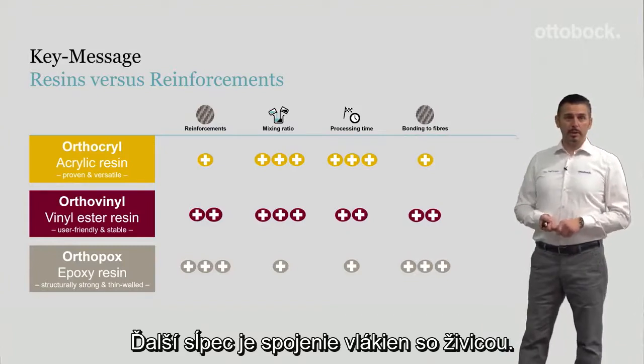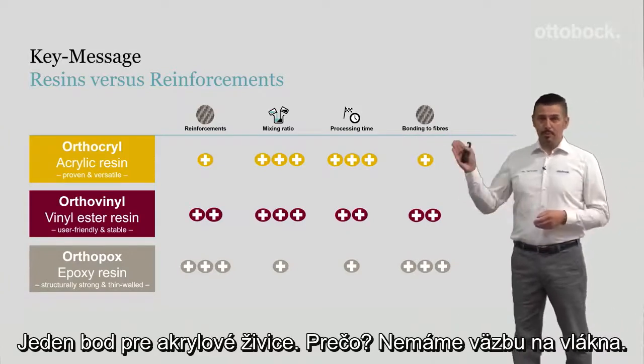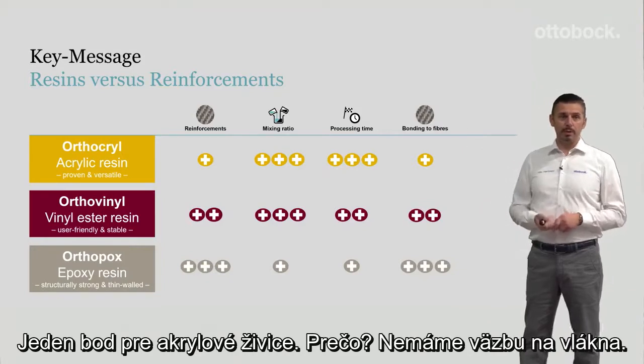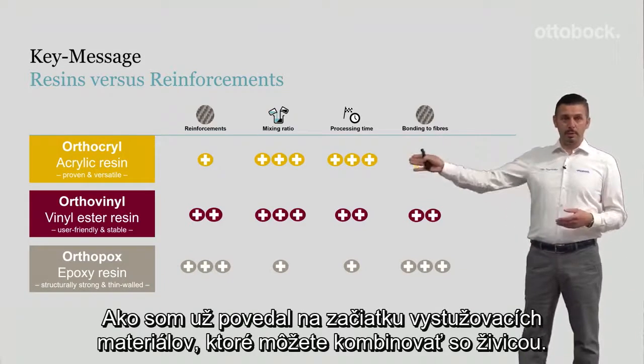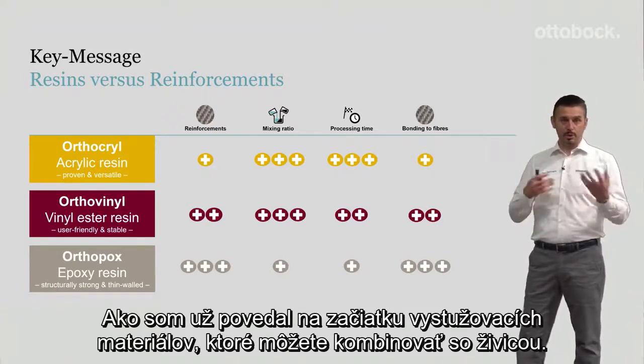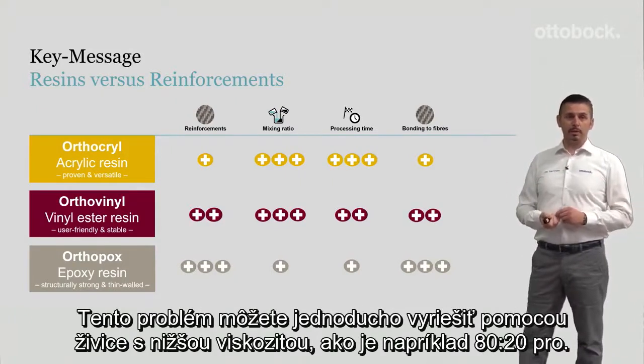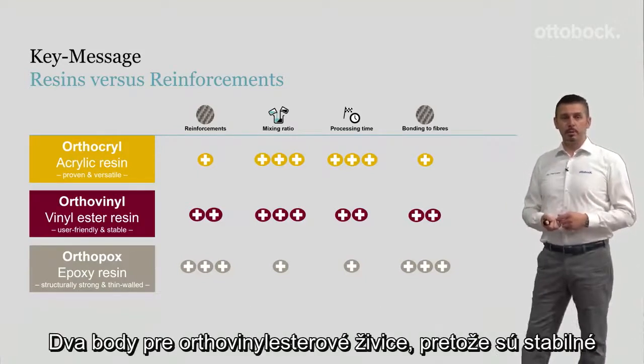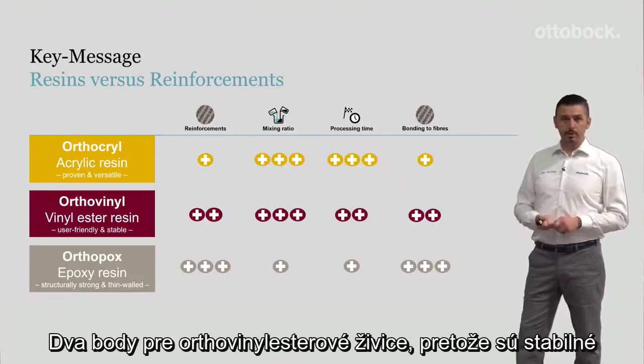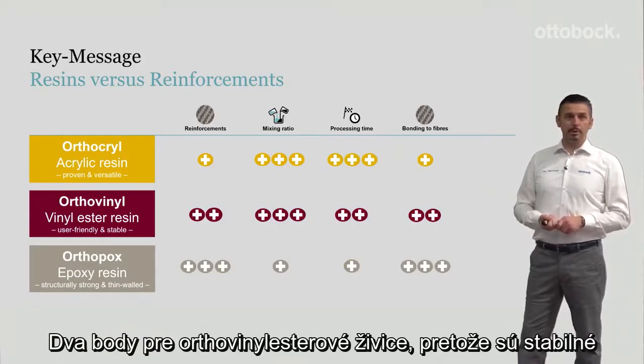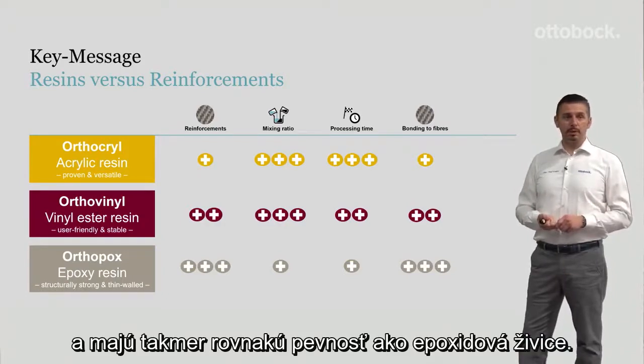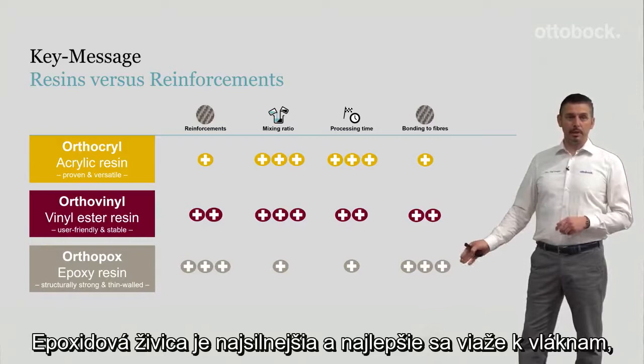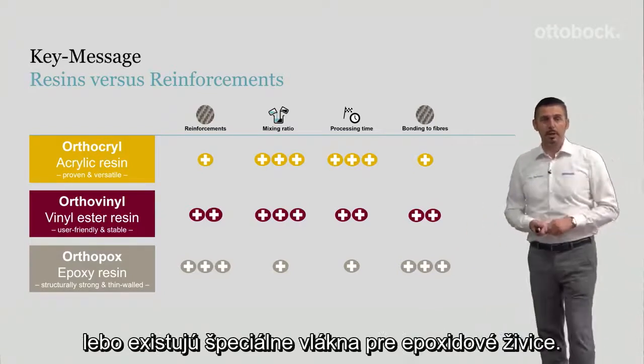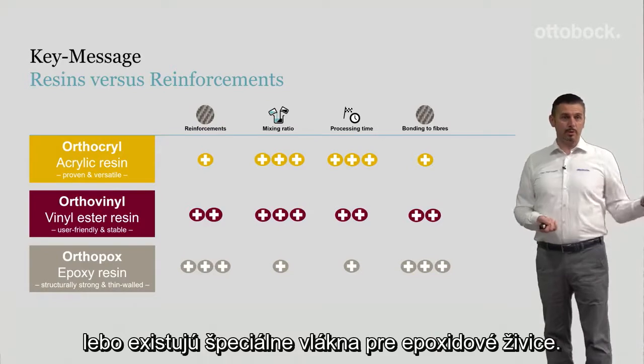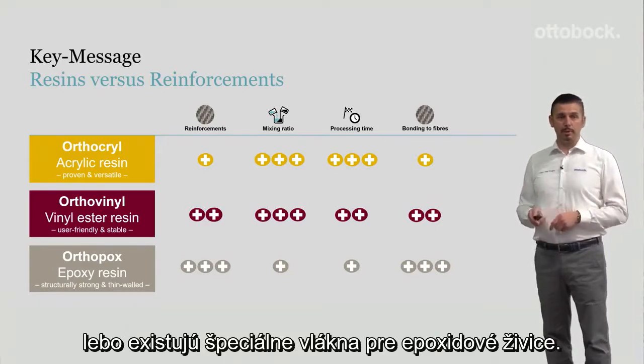Next one is the bonding of the fibers to the resin. 1 dot for the acrylic resins. Why? We have no bonding to the fibers. As I said at the beginning, for the reinforcement materials which you can combine with the resin, you can just solve this problem with a lower viscosity resin like the 80:20 Pro. 2 dots for the orthovinyl ester resin, because it's stable and has nearly the same strength as the epoxy resin, but the best strength and the absolutely best bonding to the fibers has the epoxy resin, because we also have special fibers for the epoxy resin.